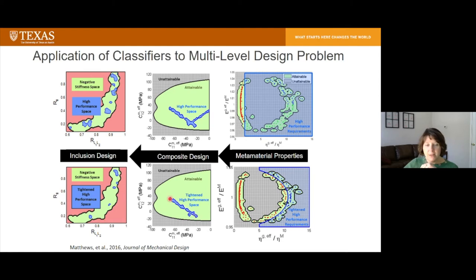You'll see a linear relationship here, which seems like it might indicate that our simulations are not performing quite right. But on the contrary, this actually matches some theoretical predictions that suggested that this type of performance should be seen from materials with constant bulk stiffness, bulk modulus, which is exactly what you're seeing here.